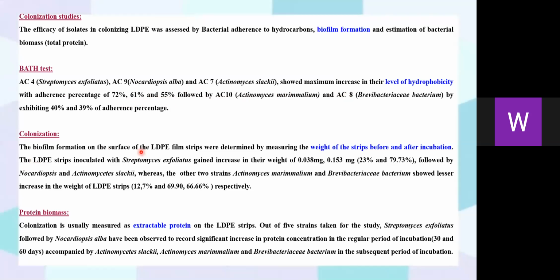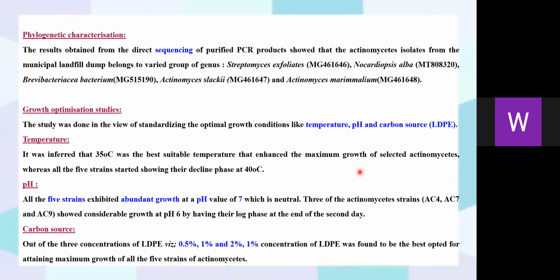Colonization study: biofilm formation on the surface of LDPE film strips was determined, and the strips inoculated with Streptomyces exfoliatus gained an increase in weight of 0.038mg and 0.153mg, followed by Nocardiopsis and Actinomyces, whereas the other two strains showed a lesser increase in the weight of LDPE strips. Protein biomass: out of 5 strains taken for the study, Streptomyces exfoliatus followed by Nocardiopsis alba recorded a significant increase in protein concentration over the incubation periods of 30 and 60 days, accompanied by the others, Actinomyces marimmalium and Brevibacteriaceae bacterium. Phylogenetic characterization was done by direct sequencing of purified PCR products, and the actinomycetes isolated from the municipal landfill dump belonged to a varied group of genera: Streptomyces exfoliatus, Nocardiopsis alba, Brevibacteriaceae, and Actinomyces.